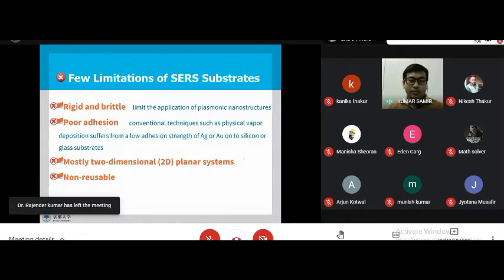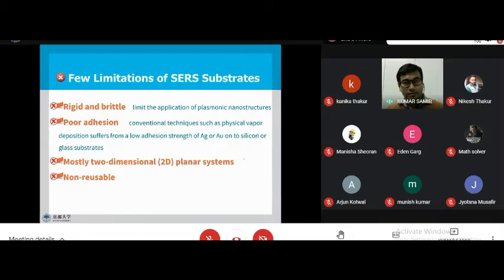And also, mostly silver and gold are deposited on silicon, and they have very poor adhesion with the silicon and glass, and they can easily peel off. So we have to use another layer, like titanium or chromium, as an adhesion layer. So that's an additional step in the fabrication process.